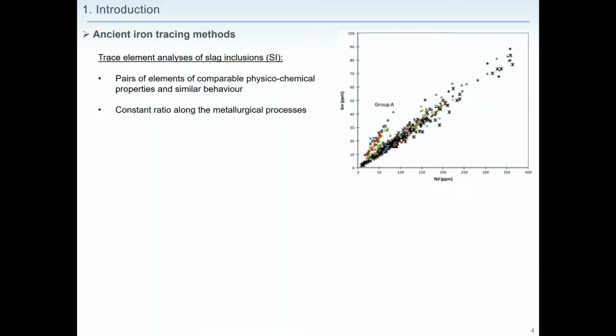The classical way to trace ancient iron is to analyze the trace element composition within these slag inclusions and to compare this composition with that of slags and ore samples from archaeological sites or ancient mines. So we can determine some pairs of elements which will behave similarly during the reduction process, and which will have a constant ratio all along the metallurgical process. In this example for samarium and neodymium, the samples plot in distinct lines corresponding to different provenance.